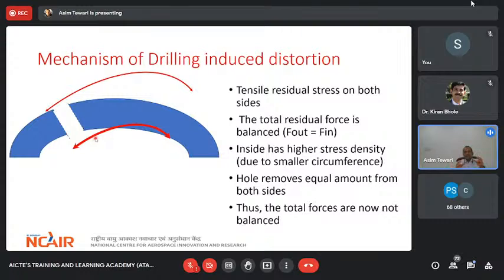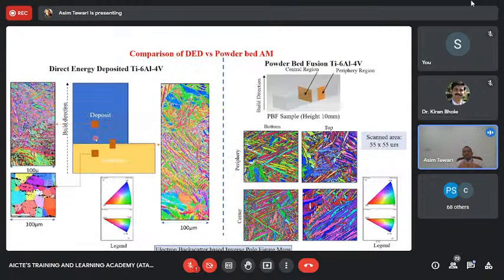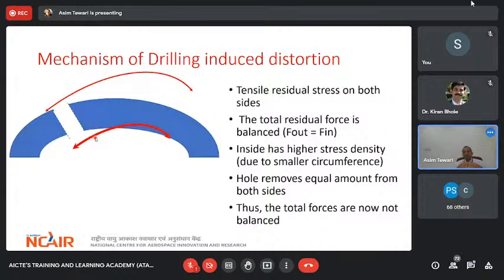Because of that, since you have removed that material, you've removed more material inside for the stress level. So the same amount of material is removed, but that material had higher stress. So you have removed more stress from inside as compared to outside. And that leads to the opening of this. So now the stresses are no more balanced. So outside has a higher tensile stress as compared to inside, because you have removed some of the tensile stress from outside and more than that from inside.